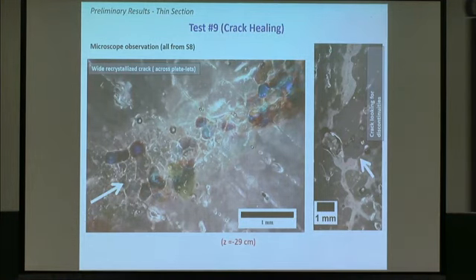If we look more closely here, we see the platelets. You can see that this is 1 millimeter over here, and we are now at the same depth. And in this case, where this thin section is taken from, we can see that the crack has been running over here, so actually transverse to the platelets here. But we can also see that it's refrozen. It's healed. As you can see, we have more or less solid ice here, so there's recrystallization.